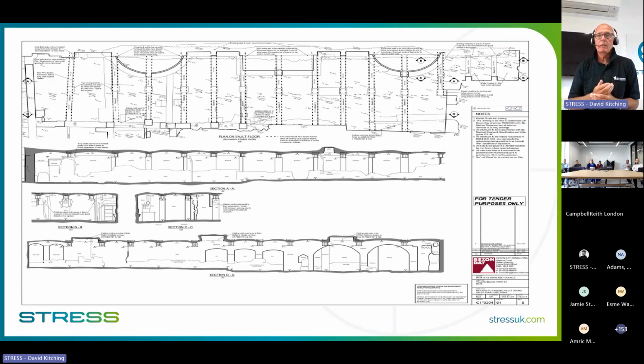And the composite beams are made up of two steel I-beams side by side, butted together, surrounded with concrete. And the problem was they didn't grout up between the two steel beams, which means obviously you're in an area of high humidity because of the springs, relatively warm temperatures as well because they're hot springs, with a slight sulfurous component to them. Absolute nightmare for corrosion. So wherever they were slightly exposed, which tends to be the ends, that's where the corrosion was occurring. And the factor of safety on York Street could not be guaranteed. Therefore, it was limited in weight, which means delivery lorries can't get to the high street, all sorts of bits and pieces. And they had to come up with a solution for strengthening or replacing those beams.